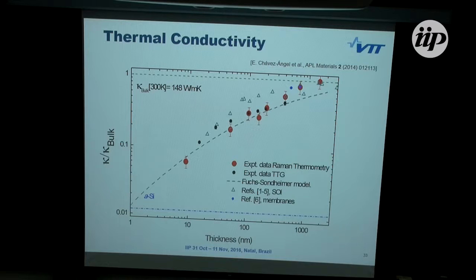So altogether, just to refresh the mind, thickness goes down, then the thermal conductivity goes down, and here is, just for reference, if I recall correctly, 70 nanometer thick polysilicon. So when the material becomes polycrystalline, of course, the grain boundary scattering increases, and this is now about 20% of the bulk single crystalline silicon. So this is also one option for applications. The thickness doesn't have to be too small, and then of course polysilicon can be doped very well also.